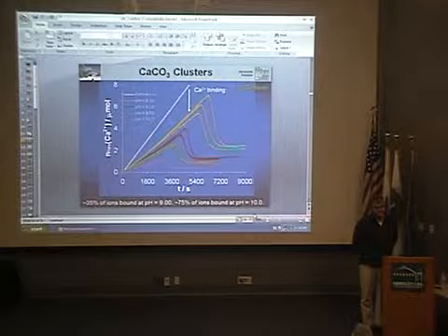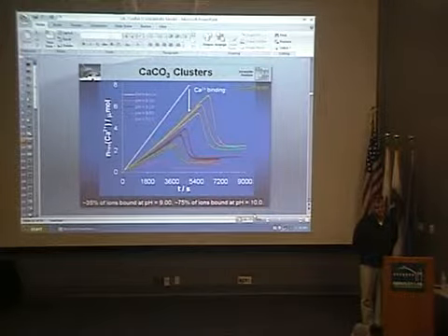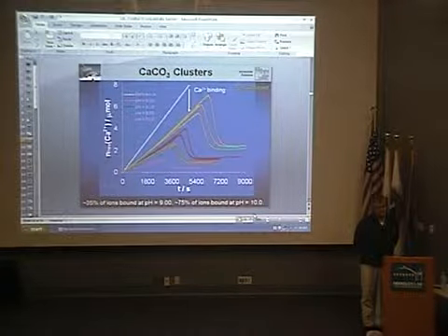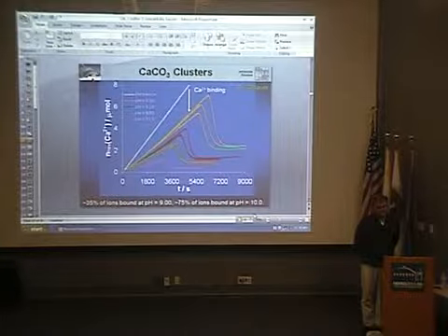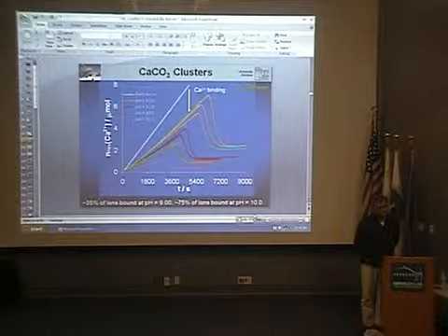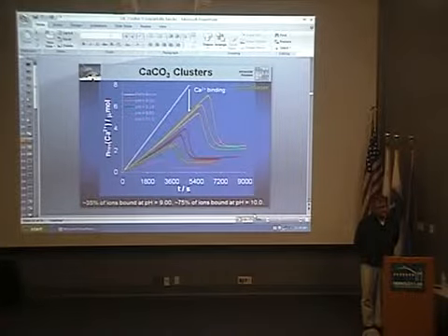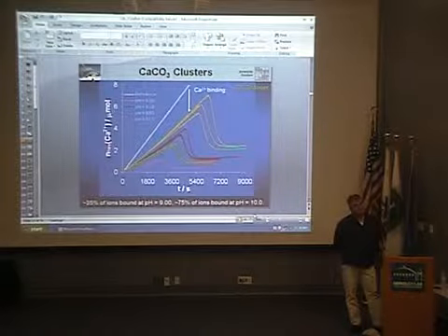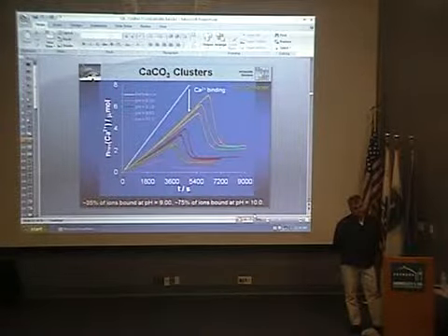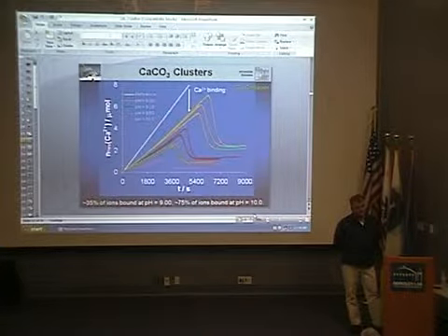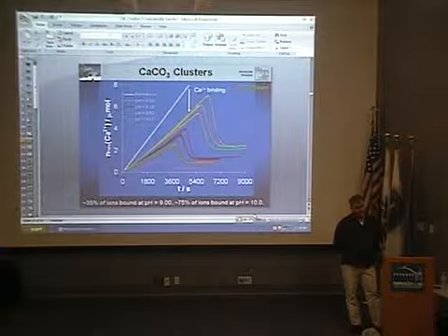So that confuses me about the statement about stability, coming back to Alex's question. If the number of clusters is only 1% of the number of ions, then the free energy of the clusters is higher. It's higher by log of 100. It's still lower than the bulk, but it still must be above the free energy of the ion pairs, and that's why they represent a small fraction of the total number.